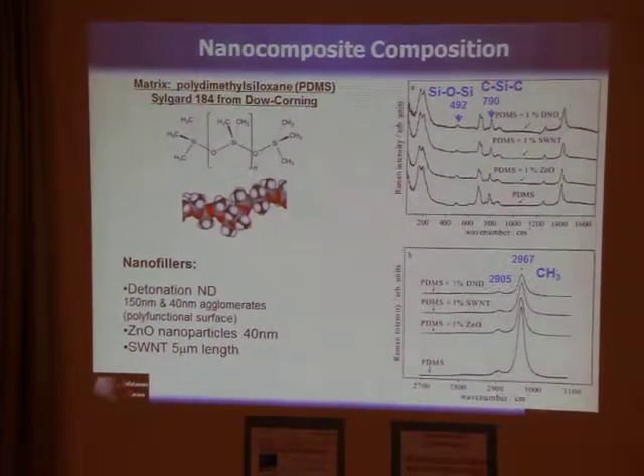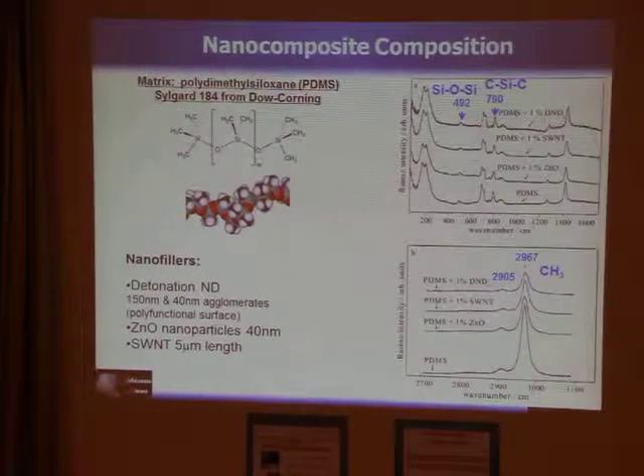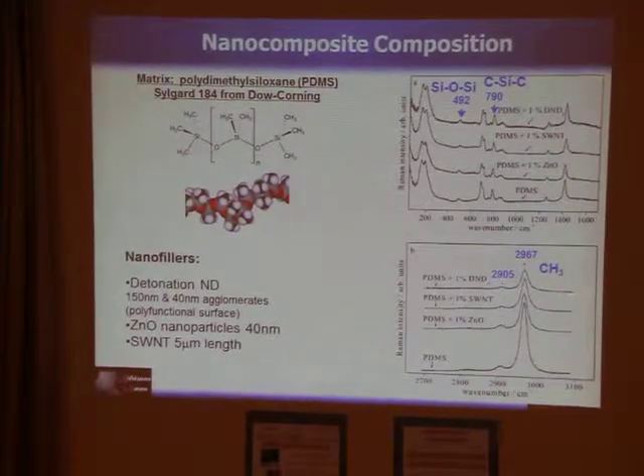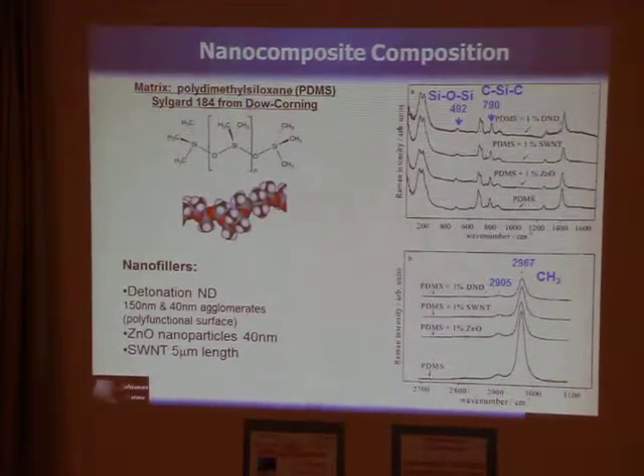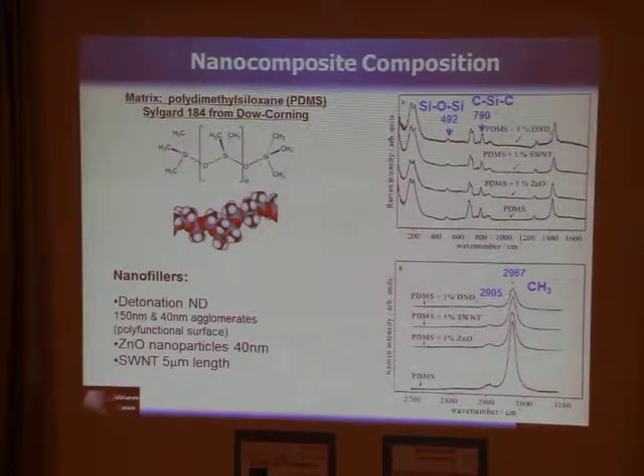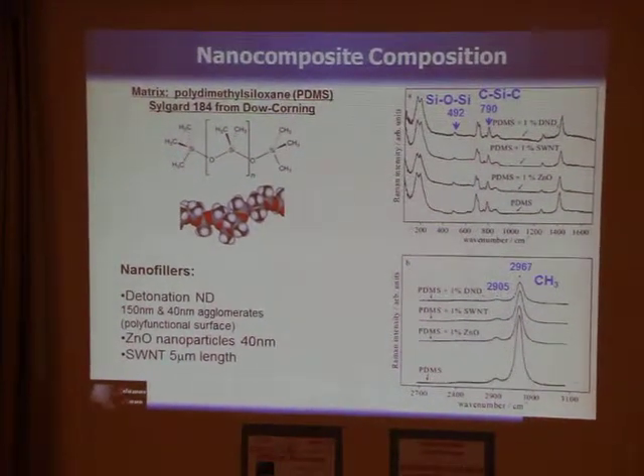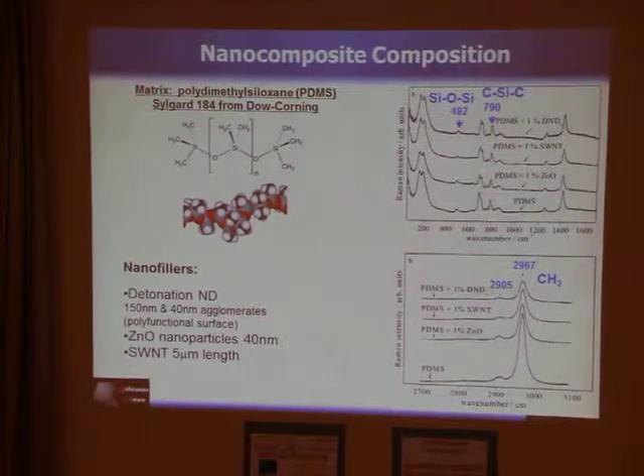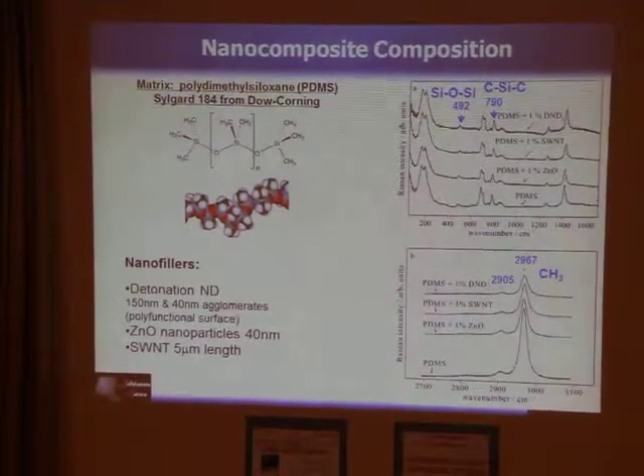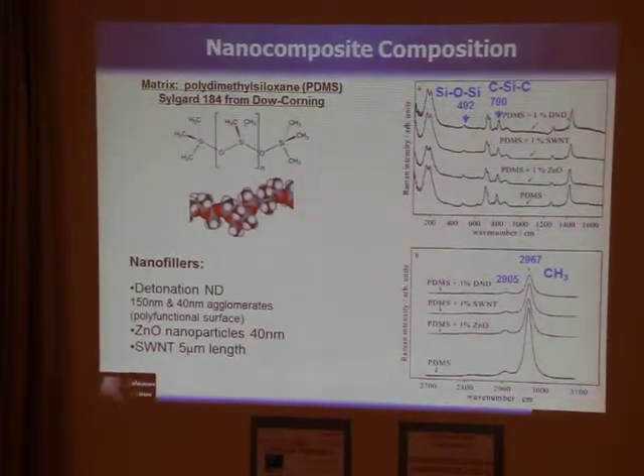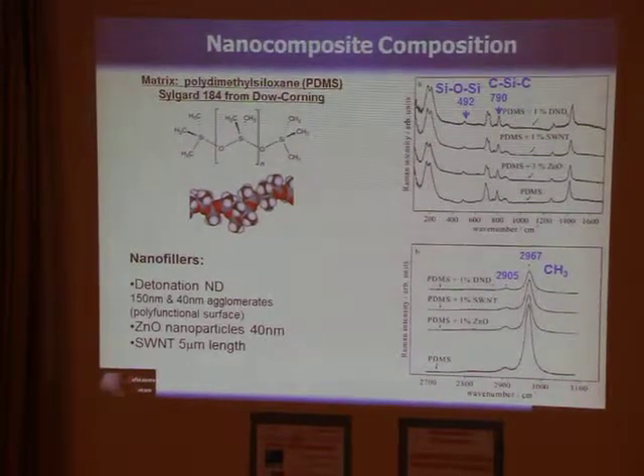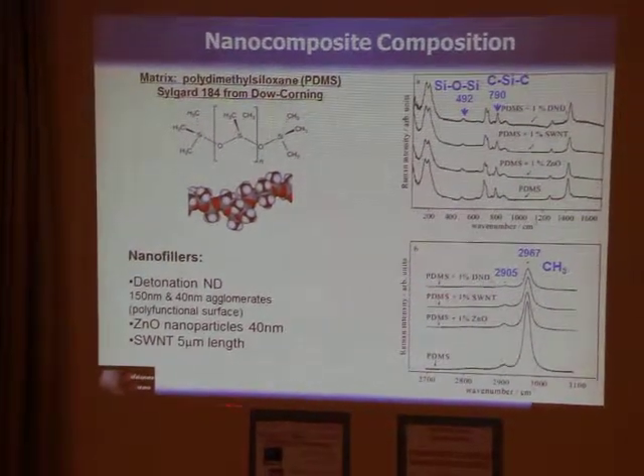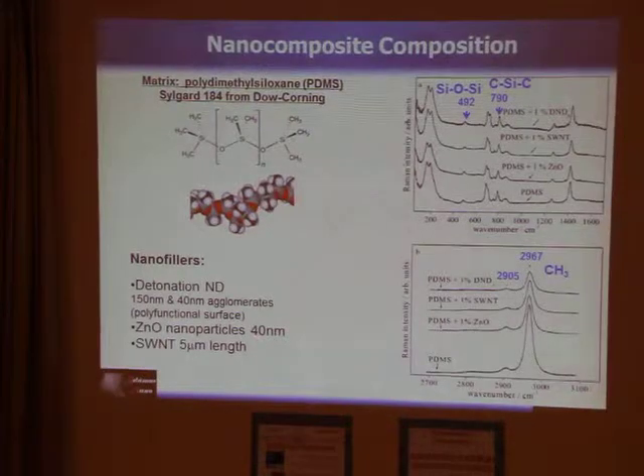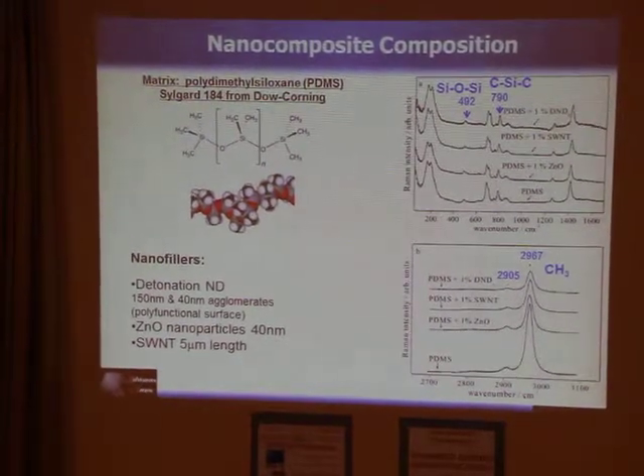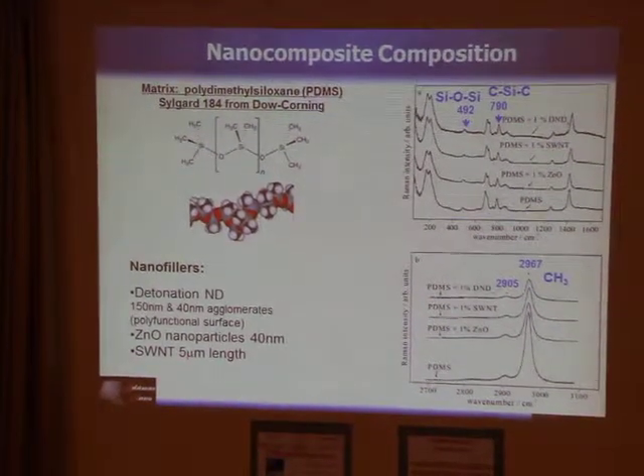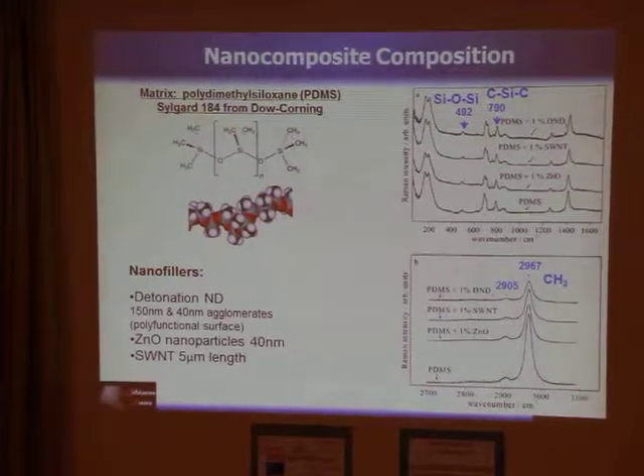Most results are shown for the polyfunctional surface. That means that they contain different types of surface groups. But we also did carboxylation and silanization of surface groups. I show at the end results for functionalized nanodiamond. And we used zinc oxide nanoparticles 40 nanometers in size, and single wall nanotubes 5 microns in length.